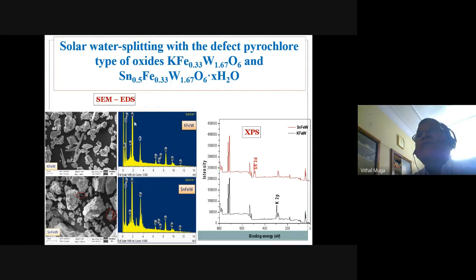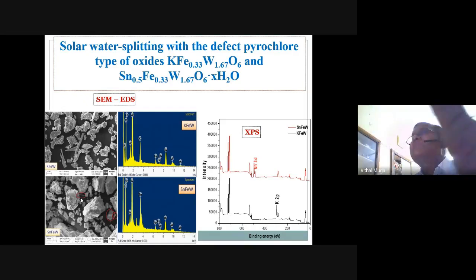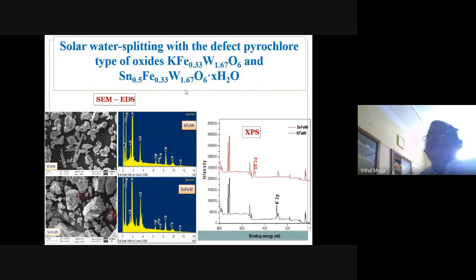Now you look at when we prepared, this is KFEW. This is the FESEM diagram. Now, if you substitute with the tin, once again it doesn't change its morphology. Morphology remains the same, but potassium disappears and tin appears. Now you see that tin is appearing here. Potassium is here, but potassium disappears, tin appears when you stir it with a tin chloride solution.